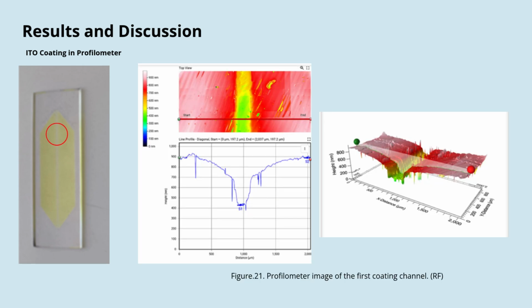Using the profillometer, we measure the thickness and roughness of the ITO coatings. The first coating, done by RF's power supply, when measured in the profillometer showed that the coating was mostly evenly distributed over the glass slide. The gap for the flow channel is prominent. It shows a thickness between 600 nanometers and 700 nanometers.